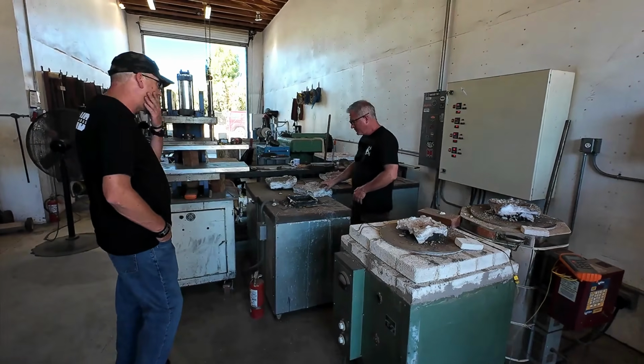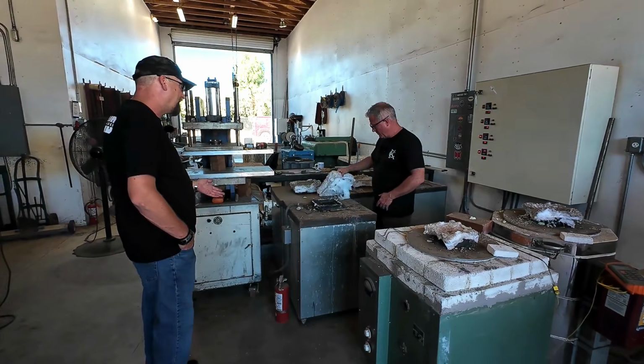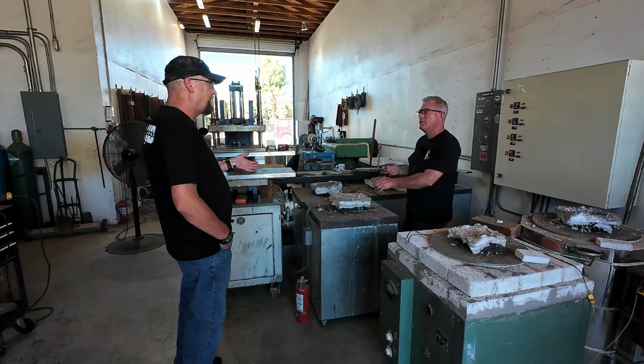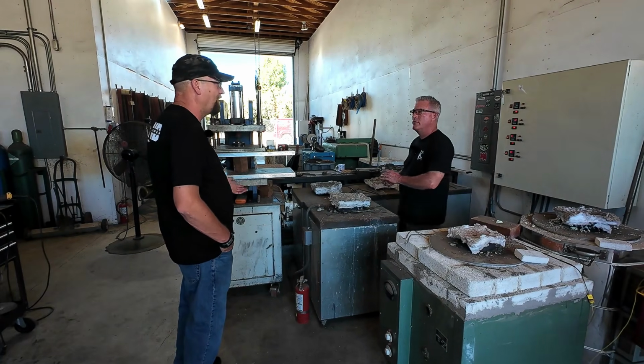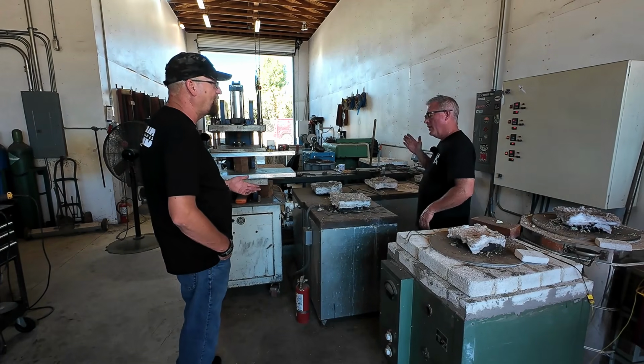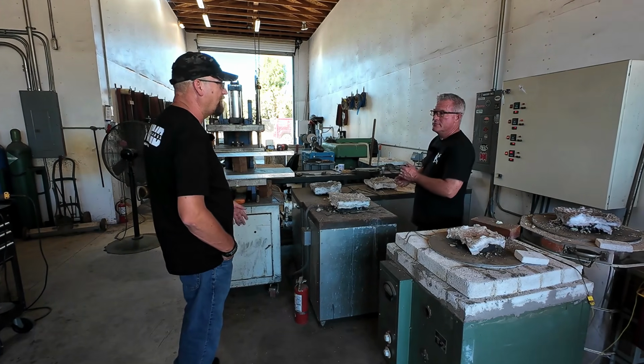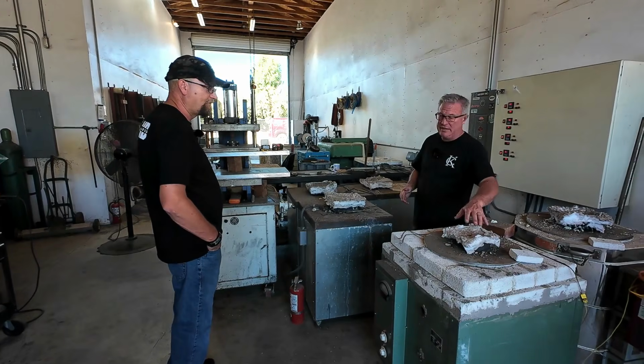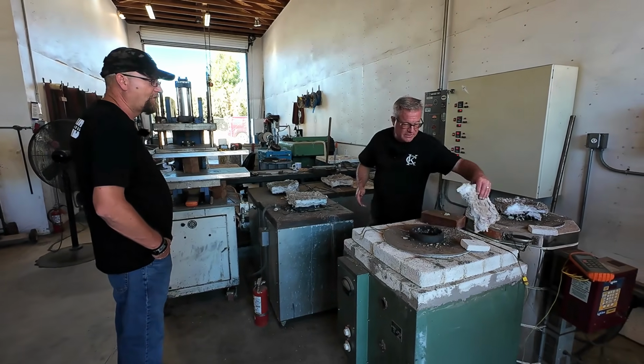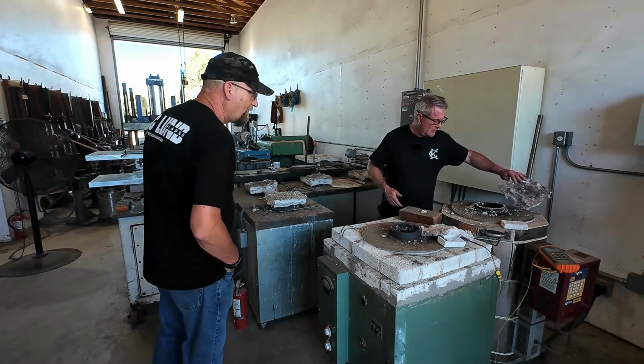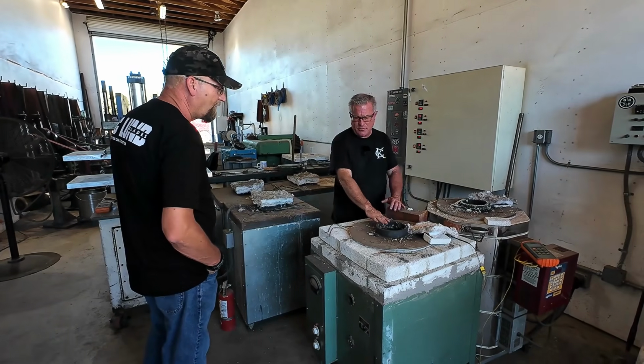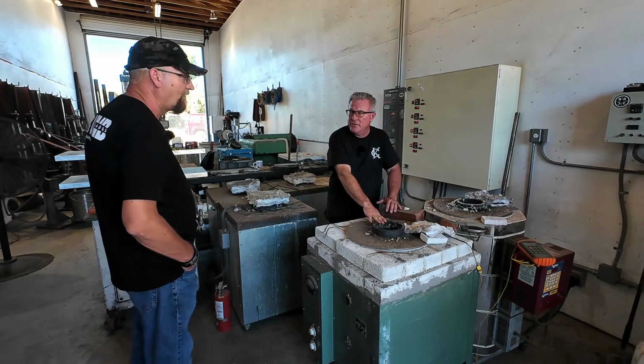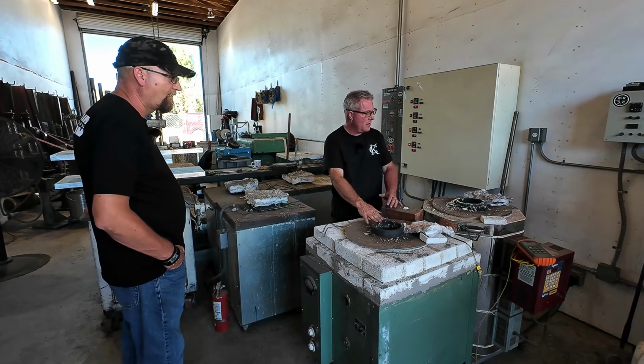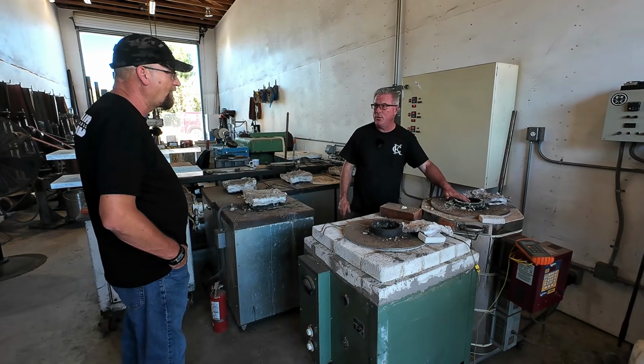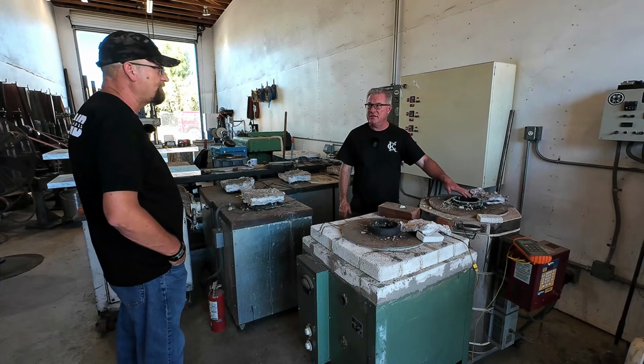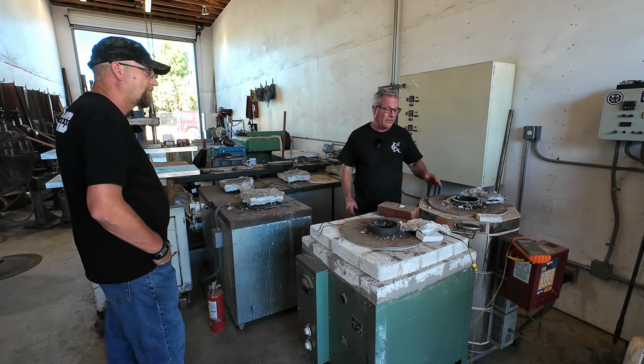And I would imagine with the salt, because you're in a liquid state, when you're getting up to these higher temperatures, you're not going to build up scale or anything like that because you're in a completely oxygen-free environment. Right, especially when you come from high temp salts. Like these salts, this one runs up to about 1650 degrees Fahrenheit. Usually I don't use it past 1500. This one will run up to 2150, so I can do stainless steel heat treating in this.